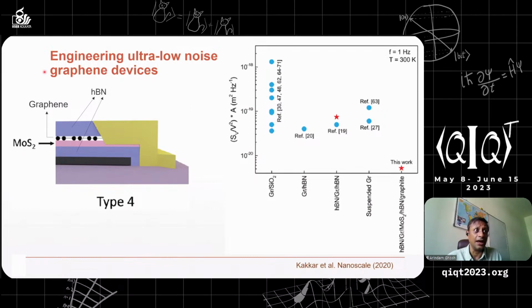And there are contacting strategies. For example, you see here what we have done. This is called edge contact. Essentially, you don't put contacts on the surface of graphene. You make contact from the side of it. You etch it down, you open the carbon atoms, and you make the metal atoms interact with the carbon atoms from the side. That seems to reduce the contact noise quite a bit, and we found good results.